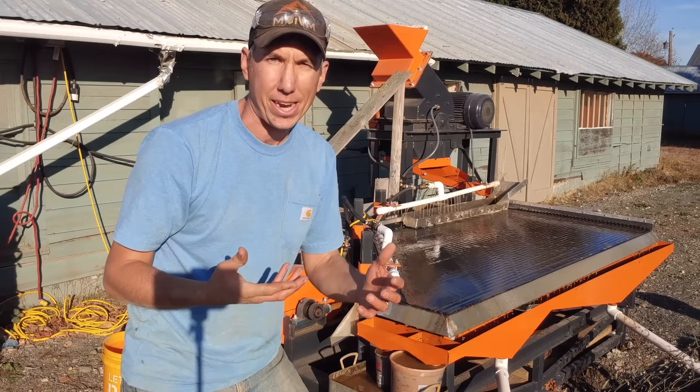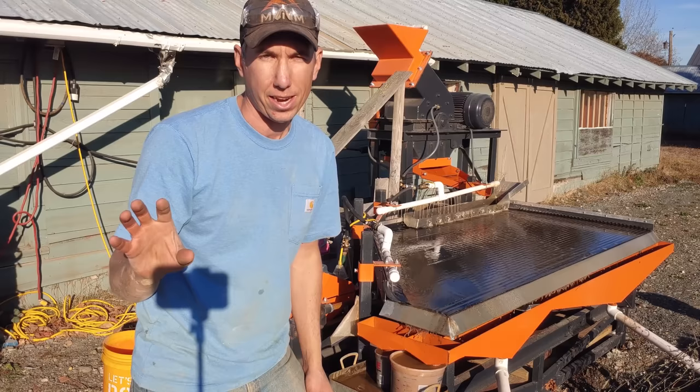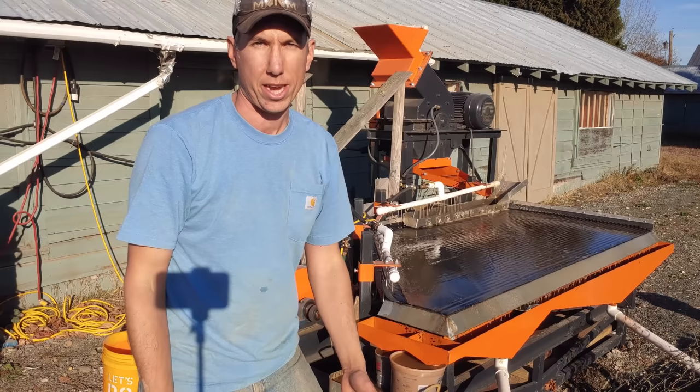One is something called the nugget effect. When you assay for gold, if there's a super, super rich area in the vein and you get a little piece of that, it can throw off the whole assay and kind of skew your results to show way more gold than if you just go in and take the whole vein. So that might be part of it.